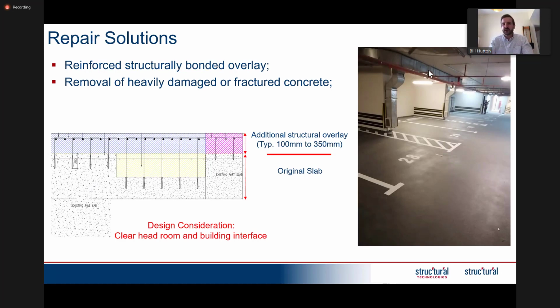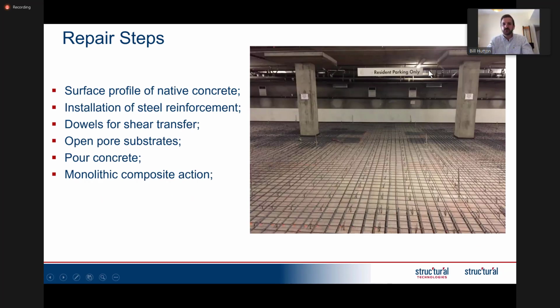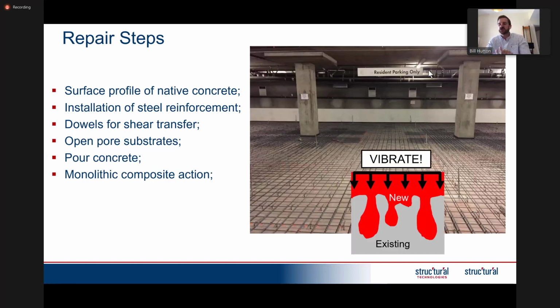So the steps for this repair, which are very simplified: you require the correct surface profile on the existing structure, or the native concrete, and that's generally CSP 6, which is a 6 millimeter amplitude. You would then install the new steel reinforcement because it's a reinforced bonded overlay. You would need to install dowels to make sure you have correct shear transfer. And then, like we discussed before, you want an open pore substrate, so you need to make sure that the existing structure is super clean and all the pores are open, so that once you pour the concrete, you can get this monolithic composite action. You would probably vibrate the concrete to make sure that the repair material gets into the pores of the existing structure.